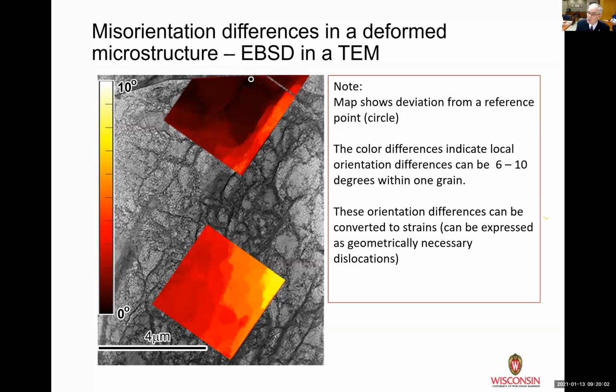Now, the way we've plotted it in this case is we've plotted it with respect to the reference point. And the reference point is actually this white circle, or this black circle with the white border that you see up at the top. Everything is done with respect to that white dot. So what you will actually see is this area down here. If you were to come from the top to almost the bottom, you're seeing a local rotation of 10 degrees.